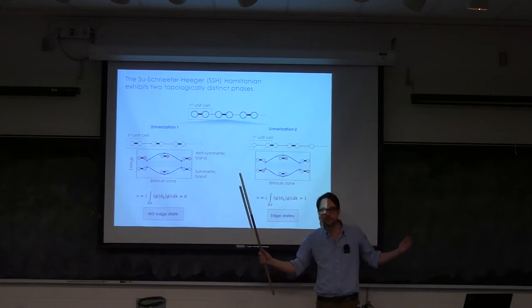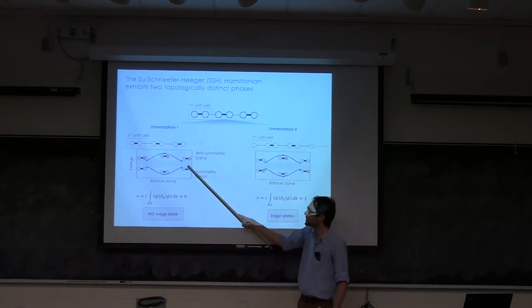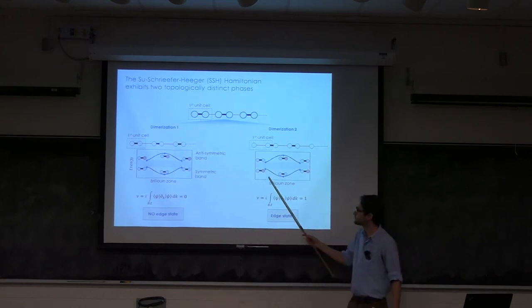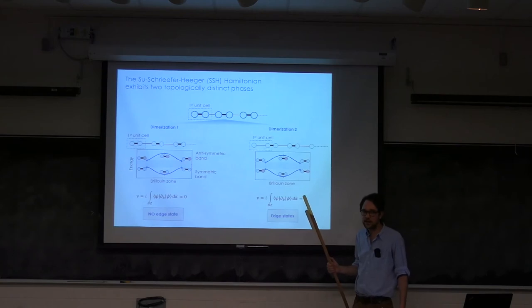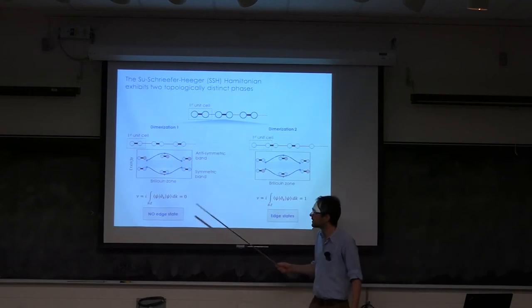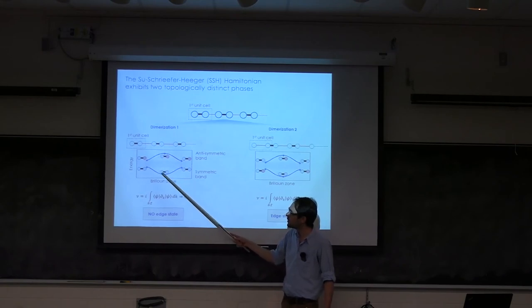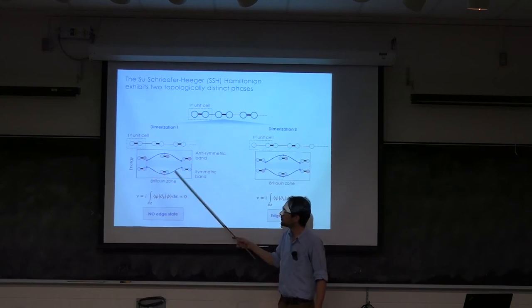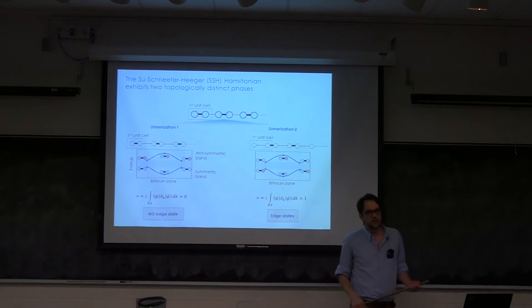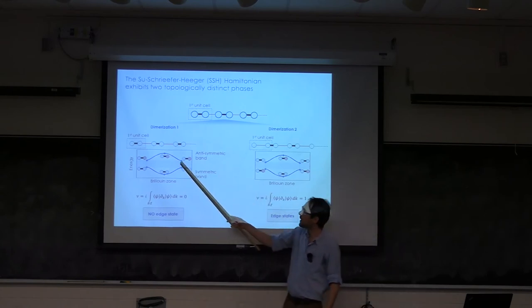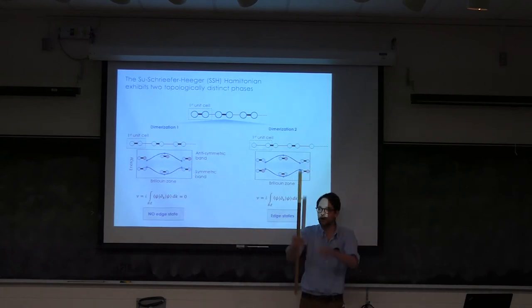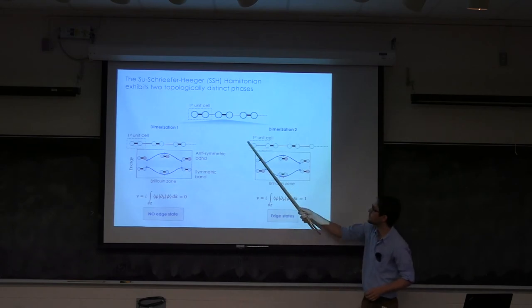So if you have an infinite bulk lattice, there's no difference. You're going to have the same band structure, formed by two bands because you have two atoms per unit cell. Now, if you look at the eigenfunctions, you will see that if you define the unit cell like this, at the center and the edges of the Brillouin zone, you have the wave function evolving in phase, because this is a bonding band, whereas the upper band is formed by atoms or pillars where the wave function evolves out of phase, and this is true throughout the Brillouin zone. This is not the case for the second case, where you define the unit cell not within the dimer but within a weak link. So you should see these.